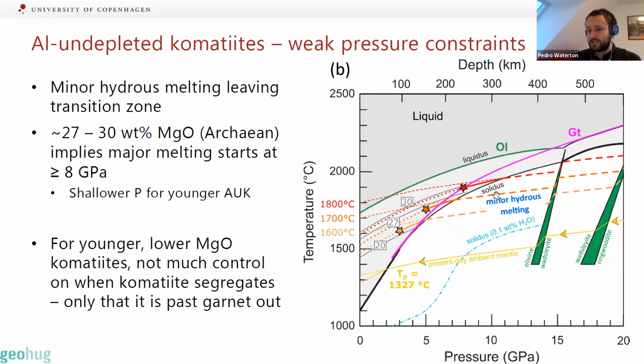But then there's no significant melting until you hit the dry solidus. And because these have generally between about 27 and 30% MgO for true Archean aluminium undepleted komatiites, this would imply that the major melting starts at pressures of higher than 8 gigapascals. And again, it can be up to 11, same ballpark as the aluminium depleted. For younger aluminium undepleted komatiites, and all Proterozoic and Phanerozoic komatiites fit into this group, then we obviously have shallower pressures and lower MgO contents.